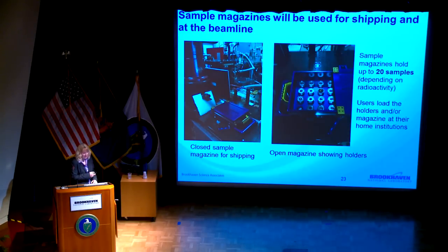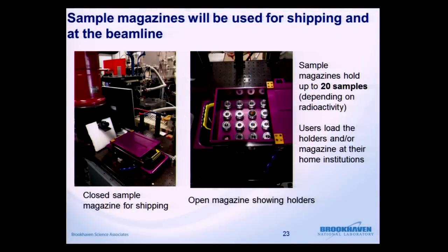These are the sample magazines. These can be used at the beamline. So this is our sample magazine for radioactive materials. It's magenta and yellow, the colors for that. And this shows a sample loaded in the base. So these sample magazines could hold up to 20 samples depending on the amount of radioactivity.